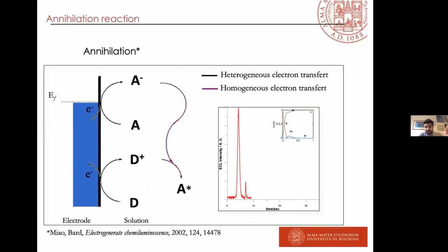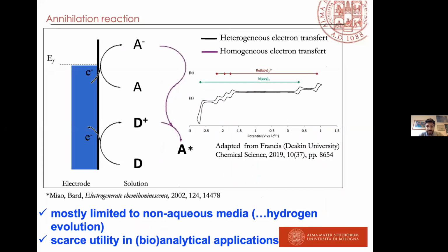And you can again switch the potential to negative and again to positive, and you generate light at each potential step. Okay, amazing. Around the year 2000, more or less, they demonstrated that they can generate ECL in these conditions. However, in this way you need a very aprotic solvent, a solvent that allows you to go to quite negative and quite positive potentials. Typically, this solvent is acetonitrile.